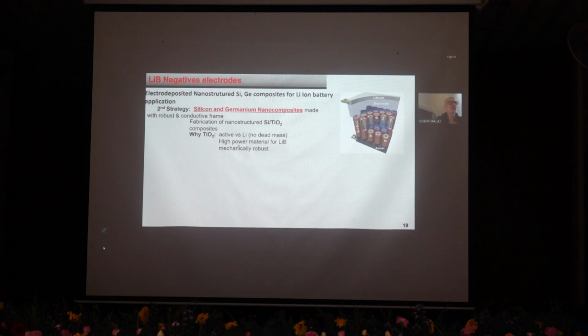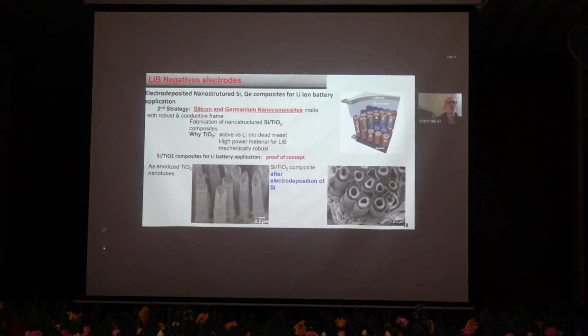So we decided to create composites made of two kinds of materials. One is the titanium dioxide, which is a conductive template, and not a dead mass because TiO2 can be lithiated. And then we cover the TiO2 with some silicon. The purpose of the TiO2 is to buffer the mechanical stress during the charge and the volume expansion of silicon during lithiation. So here we start with the anodization of titanium foil, as we saw earlier, and then we do an electrodeposition on top of the TiO2 to create those composites.